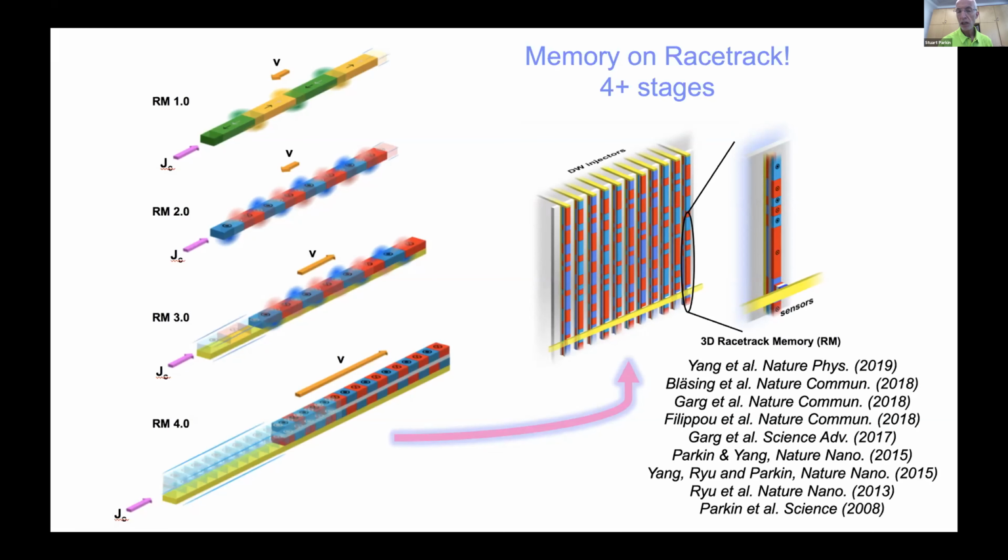Moreover, the domain walls can grow and shrink enormously because they're basically determined not by exchange and anisotropy, but by exchange and dipole fields, and the dipole fields are long ranging, and these give rise to large objects. I want to come back to that towards the middle of my talk about anti-skyrmions. Anyway, those domain walls in those early days could be moved at about 100 meters per second when we apply current pulses, and the mechanism was spin transfer torque.